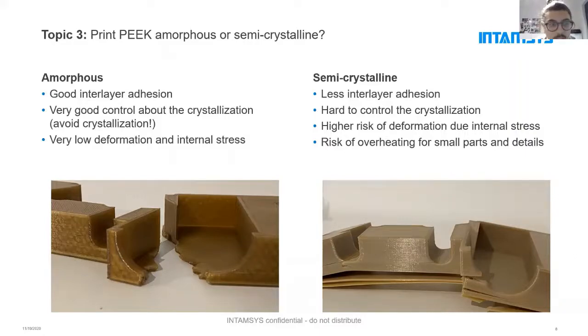If you see, on the other hand, printing semi-crystalline, this again depends a lot on the parameters. How fast do you cool? How hot is your build chamber and so on? But it gives you in general a little bit less interlayer adhesion, while it's very hard to get the crystallization on the point. And what you see on the breakage below is when you break the part, that really the layers split up. This is related to the crystallization of the bottom layer. So the layer is already crystallized, and then you put a new amorphous layer on, which crystallizes after a few seconds. And then you have two separately crystallized layers. They are not structured together.